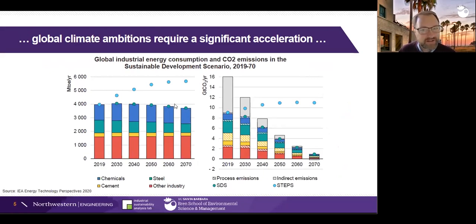But if we think about where the industry needs to go, and frankly, where all industry needs to go in a net zero emissions future, it's clear that climate ambitions need a significant acceleration. What you're seeing here are analysis results from the latest Energy Technology Perspectives report from the IEA. Cement is highlighted in yellow here. What you're seeing are the trajectories for the stated policies scenario. This is the agency's outlook for where the world may be headed without increasing its climate ambitions. And the sustainable development scenario, which you see here, is the sustainable low carbon scenario. And what we see pretty clearly is that, especially for the cement sector, shown here in yellow, emissions must be drastically reduced by around mid-century, out to 2070. So decarbonization of the cement and concrete cycle is critical.